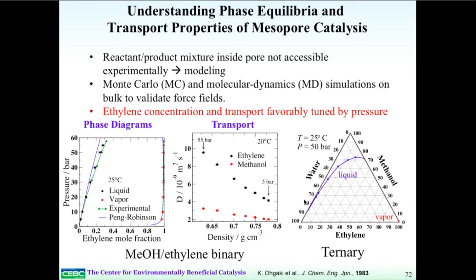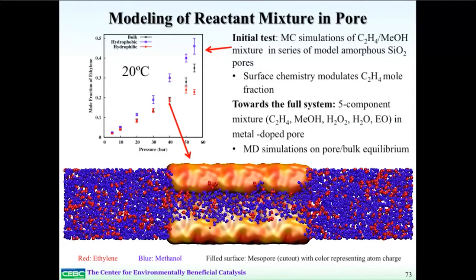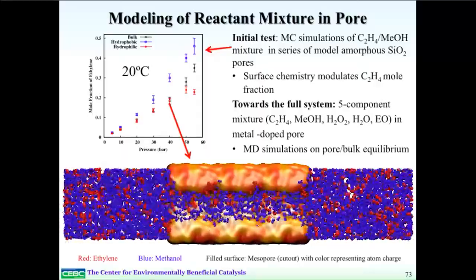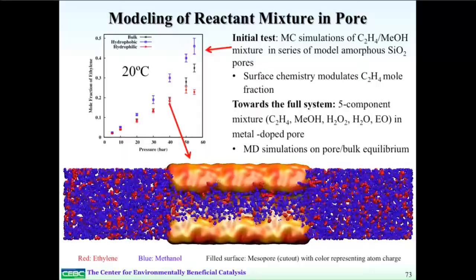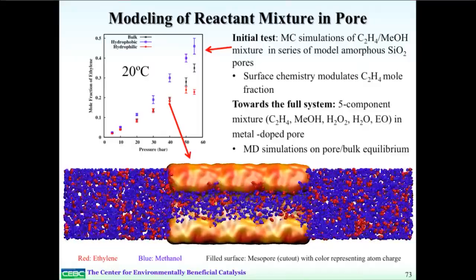But more importantly, and I'm going to have a movie here to start, we can actually model the reactant mixture inside the pore. And one of the things that we found here is that the pore surface composition can modulate the ethylene composition quite dramatically. If you look at the pore, you can functionalize these silica pores with OH groups to get hydrophilic sites, or you can have them more terminated with hydrogens or methyl groups to get hydrophobic sites.